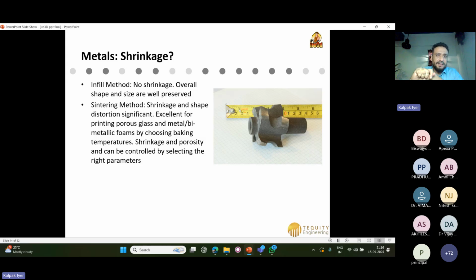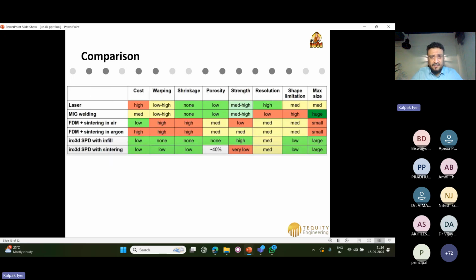All the other ways of printing metal usually are very expensive. And in the case of sintering, if you're sintering metals, you will have significant shape distortion. It will typically shrink volumetrically, and it is excellent for printing porous glass, metals, bimetallic foams, etc. Just a quick comparison. Each process has its own pros and cons, but SPD ranks well on cost, warpage, shrinkage, porosity, and most importantly cost. Because it's like 1/20th to 1/50th of other processes, or even 1/100.